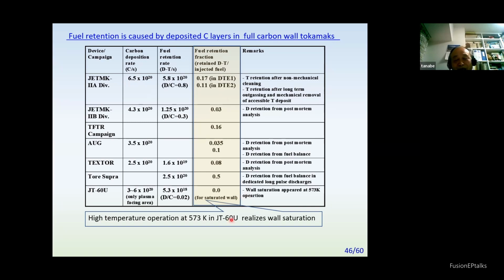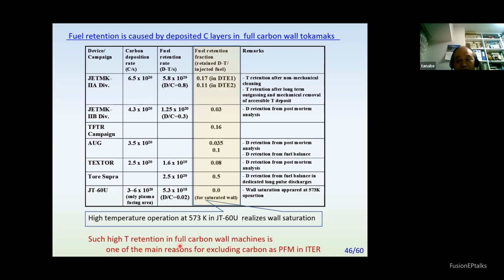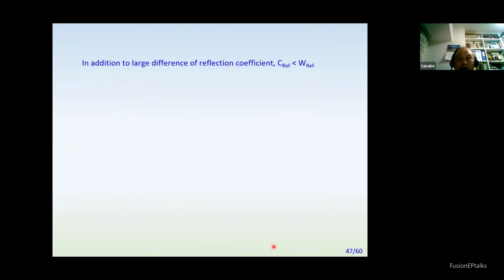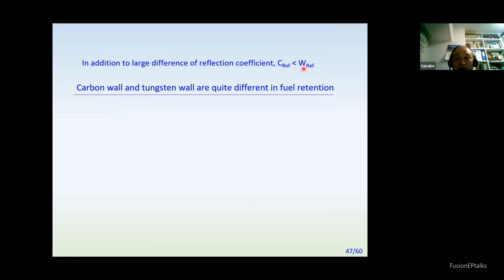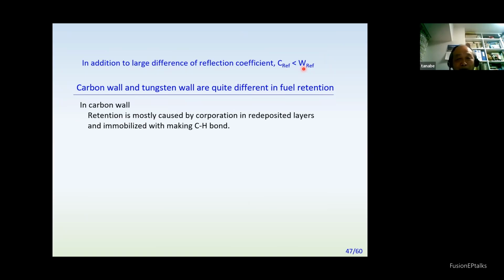So high temperature operation for a reactor is promising in this respect. Such high retention in carbon machines is one of the main reasons for excluding carbon as PFM in ITER. In addition to the large difference in reflection coefficient, carbon and tungsten are quite different in fuel retention. In carbon, retention is mostly caused by incorporation in redeposited layers, which are immobile due to making a CH bond.